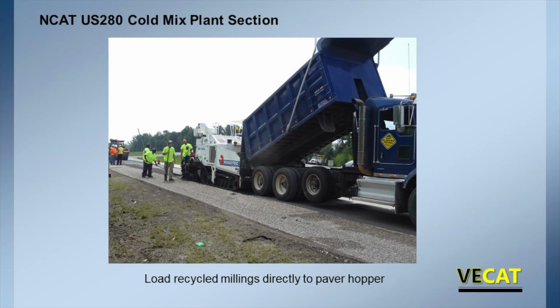So we take that 20-ton truck, deliver it into, this is a straightforward strike-off screed on this paver. So we're going to be paving thick and compacting down. So we're getting very little pre-compaction at a screed. And that's relative to going back to our test section. What screed are we using? If we've got a high compaction screed and we're getting 93, 96% compaction at the screed, we're probably only going to be paving 4.5 inches to get back to 4. If we've got a strike-off screed like this, we're probably going to be paving 6 to get back to 4. So do your test section. It's very important relative to the paver that's going to be used on the contract.